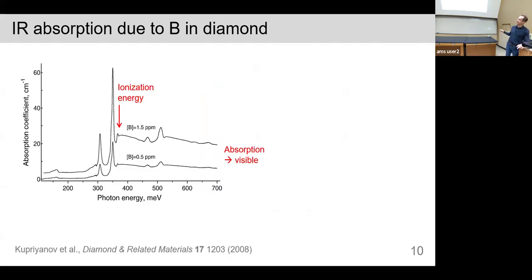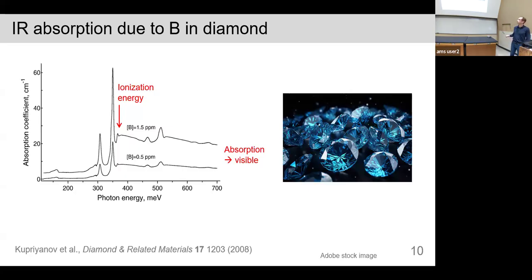Okay, it's an acceptor. It has these 1s to 2p-like peaks, has continuum absorption, and a couple other peaks that are interesting. But the point is that the threshold is 300 millielectron volts, so it's a deeper acceptor, higher energy to ionize it. It's still not in the visible, so this is all in the infrared. But if you keep looking at this absorption profile into the visible, it actually does absorb reasonably strongly in the red, and a little bit in the green, and not at all in the blue. And so that results in these wonderful blue diamonds, which are sometimes called type 2 diamonds.